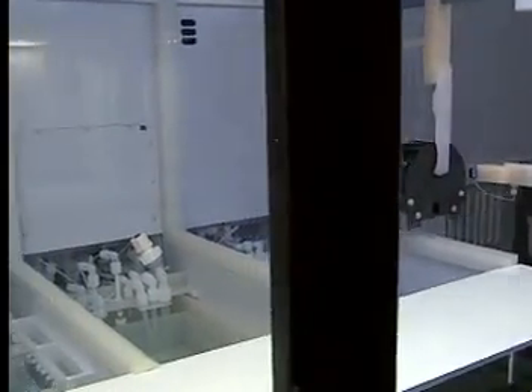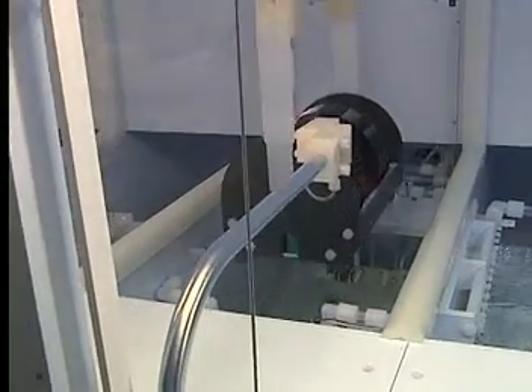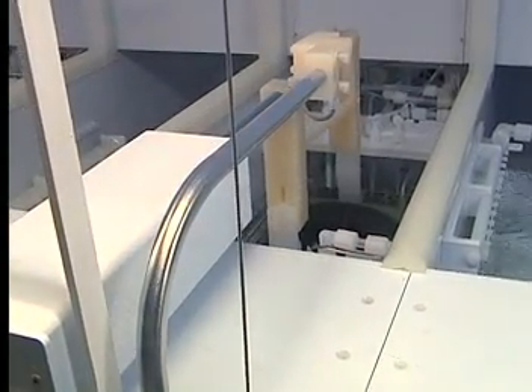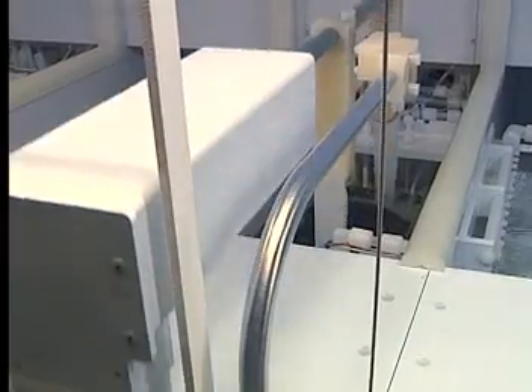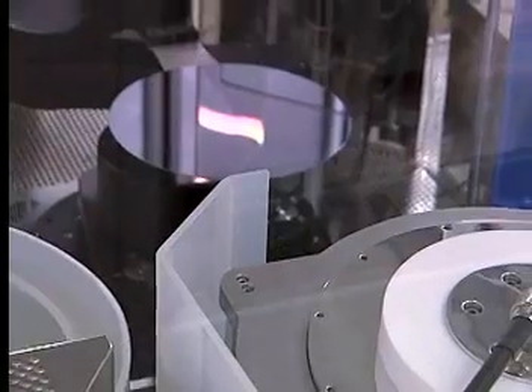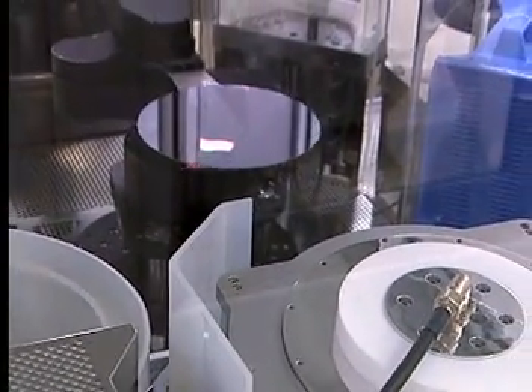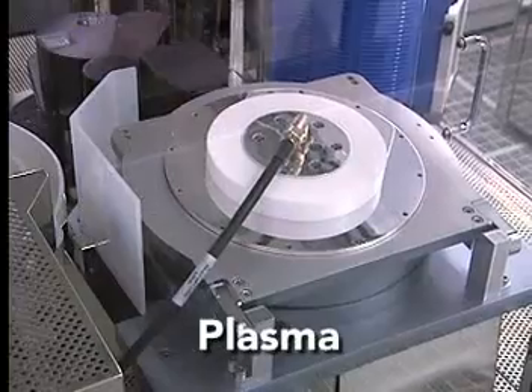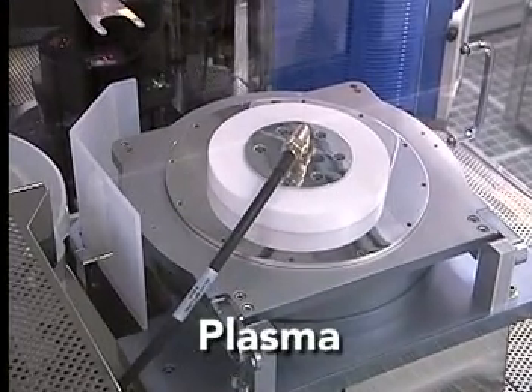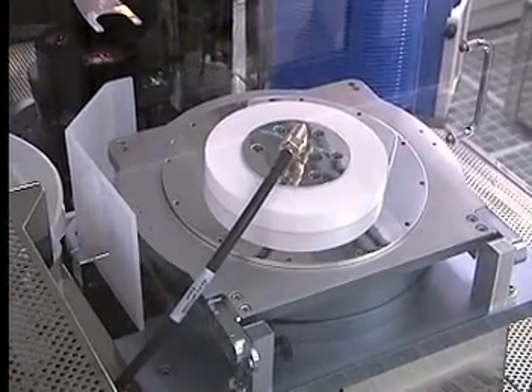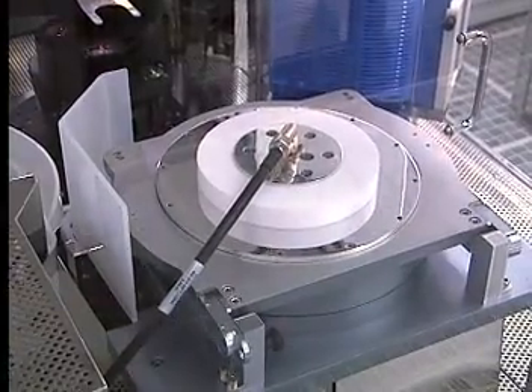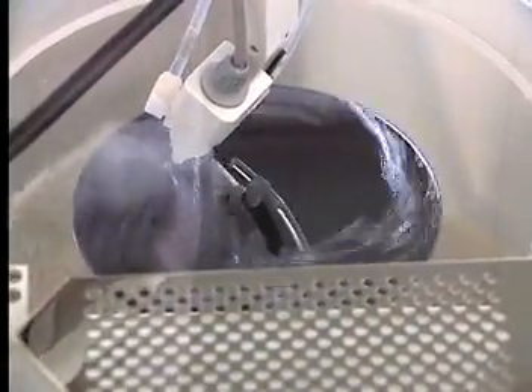Just prior to bonding, both the donor and handle wafers are meticulously cleaned to remove contaminants. These particles could interfere with the bonding process, resulting in bonding voids and other layer defects in the final SOI wafer. The first step in the bonding process is to expose the surfaces of the donor and handle wafers to a glow discharge plasma process. This process chemically activates the surfaces to produce a high initial bond strength. The wafer surfaces are then rinsed in deionized water and spun dry.